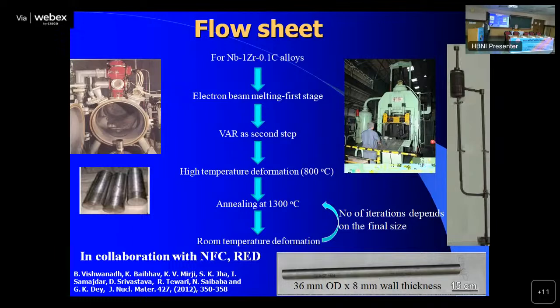I've lost two slides here, and they were on niobium-based alloys, on zirconium, niobium 1 zirconium 0.1 carbon alloys. Just to summarize what those slides had, they showed the microstructure of the niobium-based alloy, that is microstructure information, and deformation information, what temperature it will deform at to make it into a product.